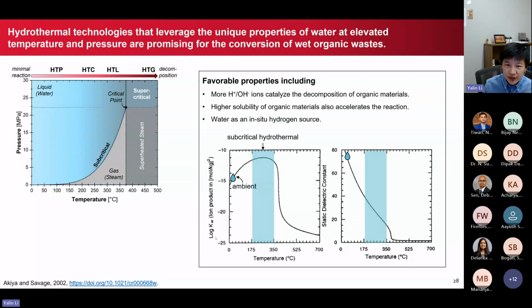And even under subcritical conditions, water will have unique properties that favor the decomposition of organic materials. That includes the increase in the ion product values, as you can see here. At ambient conditions, water has a Kw of 10 to the negative 14th. But if you go to 300 degrees Celsius, you will have much higher Kw values. The dielectric constant of water will also decrease, which means it becomes a better solvent for organic materials. This also helps to accelerate the decomposition. And then finally, water is actually an in situ source of hydrogen, and you can use aqueous reforming processes to essentially eliminate the use of external hydrogen as you are trying to make renewable fuels.